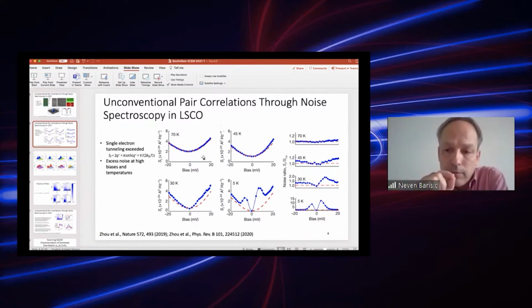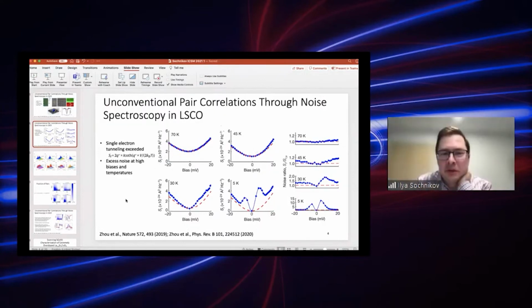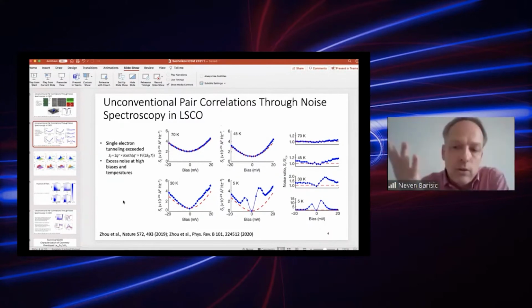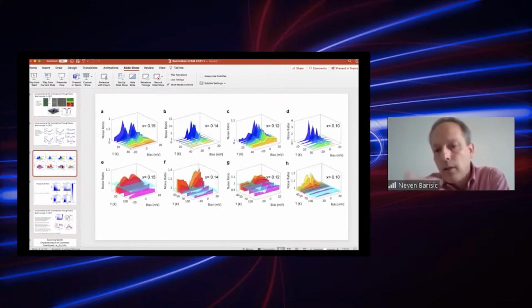Because the shot noise will see which type of carriers you have. At 70 Kelvin, there are some carriers that tunnel and they look like single electrons. There are only quasi-particles tunneling. And for me, that's kind of a nice message. And then around 20, 30 Kelvin above TC, pairs start to appear. Am I right? That's something which is kind of everywhere: around 20, 30 Kelvin above TC, you start to see pairs appearing.